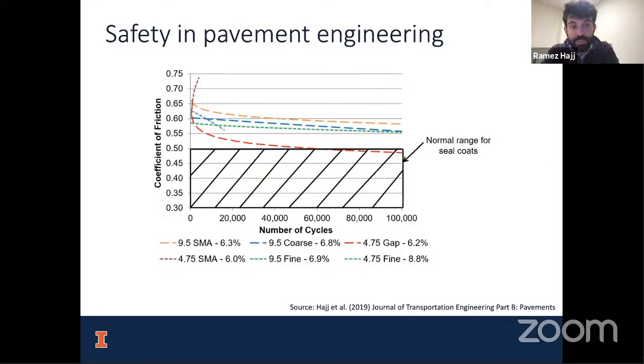However, this procedure is a little bit complicated, especially in the US, because the technology to use it had a patent on it. So we were wondering, could we use just a ½ inch of a simple asphalt mixture of different types, and could we get the same surface friction? What we realized here is actually, in 2 cases at least, no. In 2 cases, we could not. However, in 4 types of mixes, we could get pretty good friction, including 3 that were actually better friction, even after 100,000 cycles of loading, than a normal range for seal coats.